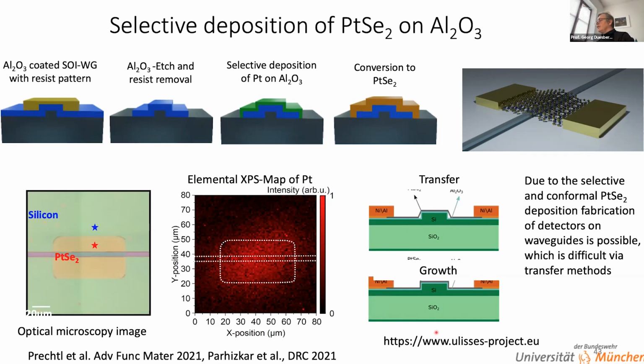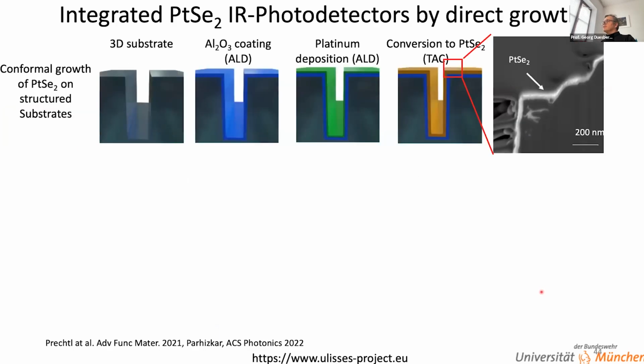Again, one of the advantages is that we have direct growth and no transfer. If you transfer onto a structured substrate, you always have the problem of reliability or ripping at the sites. And this has been pursued in this Ulysses project. So we developed basically a conformal process based on ALD coating of platinum and then the conversion.